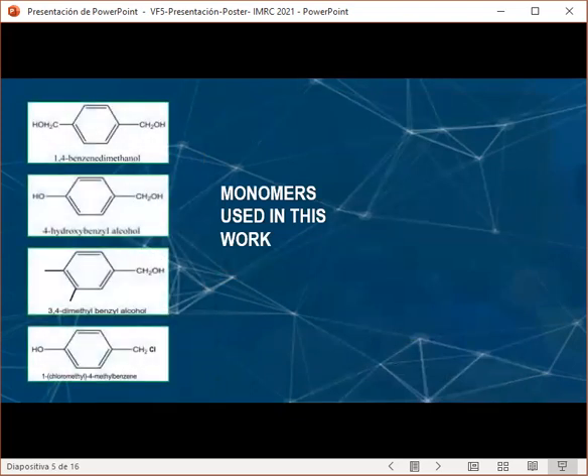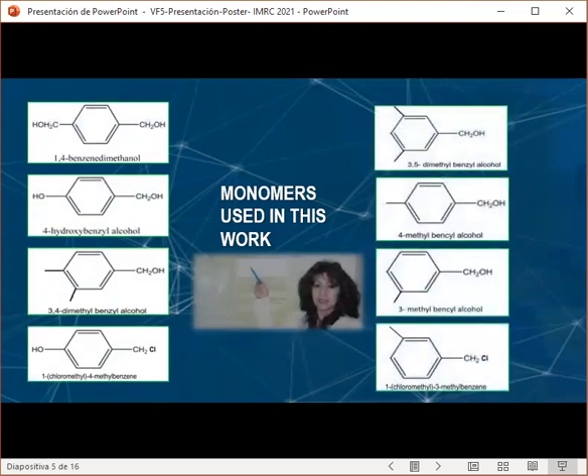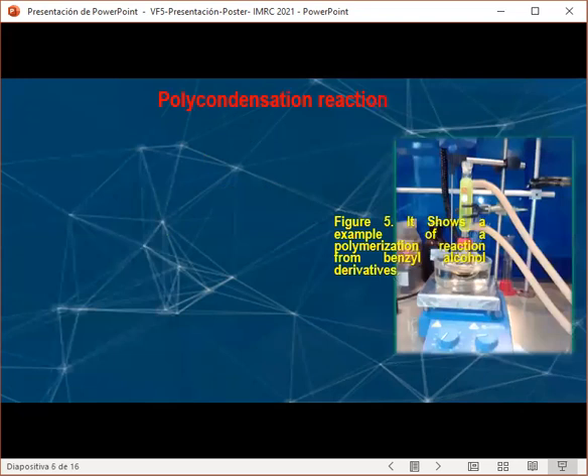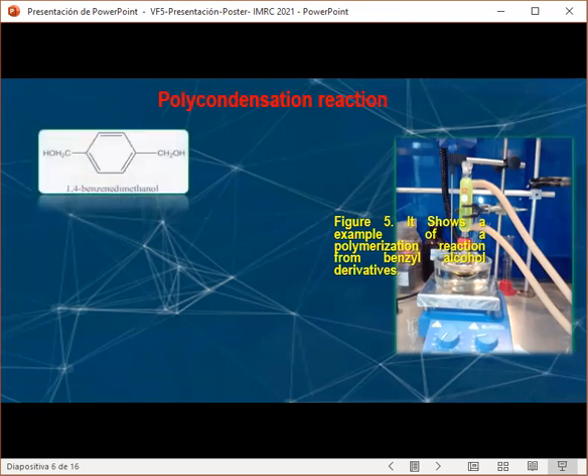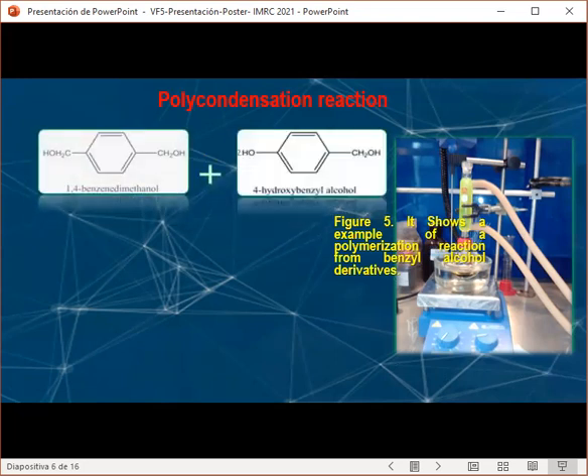In this slide, you can see different monomers that we used in the synthesis by polymerization condensation reaction, and we obtain oligomers and polymers. For example, a polymer was prepared by the condensation reaction in a ratio of 1 mole of 4-hydroxybenzyl alcohol with 1,4-benzenedimethanol, using 0.1 and 0.5 of trifluoromethanesulfonic acid as a catalyst. You can see Figure 5.